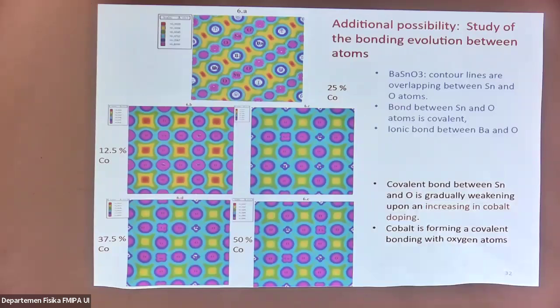I showed the possibility to completely study the electronic structures, electronic properties. But here, you can also study the effect of the doping on the different bondings existing between all atoms of the crystalline cells. And that was interesting because here we showed that the covalent bond between tin and oxygen is gradually weakening upon increasing cobalt doping, and that cobalt is forming covalent bonding with oxygen atoms. That's why these two remarks were finally the synthesis of this effect. So why do we decrease the energy gap? Because we have these two effects.